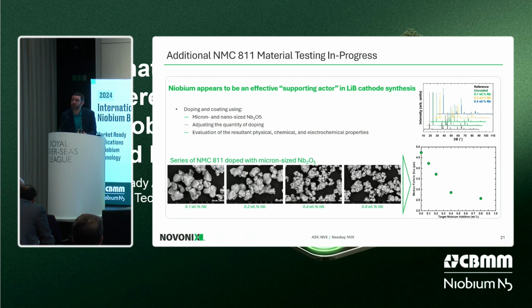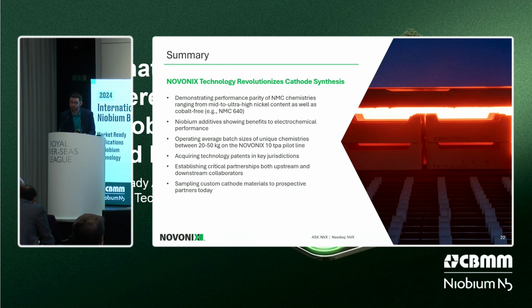So we're going to explore this further and understand a little bit more about the consequence of adding niobium oxide as a dopant material in future. So to wrap it up, what I've shown you today is that we can make competitive cathode materials using an all-dry process relative to conventional synthesis routes. We have programs that work on mid-nickel, NMC 631, all the way to ultra-high nickel content materials. We're talking 95.5. And we even have programs that are running with zero cobalt. These are the so-called 640 series of materials.